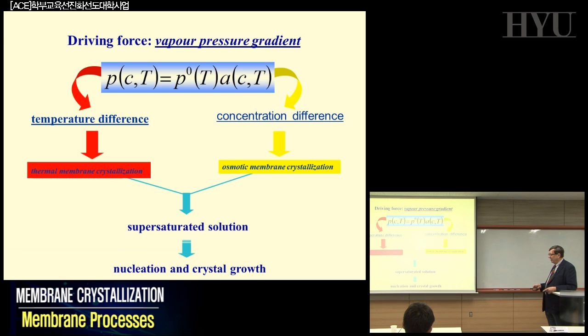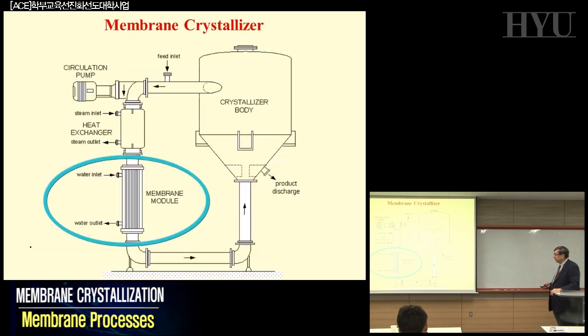That means you cannot try to grow the crystals on the membrane surface itself, except in some situation in which the value of the crystal is so high that you have no problem in changing the module or cleaning the module every 2 or 3 or 5 hours. But if you want to produce, for example, fresh water from the sea at a very high recovery ratio, that means there's a lot of salt, you have to separate the nucleation from the crystal growth. And that is a typical example.